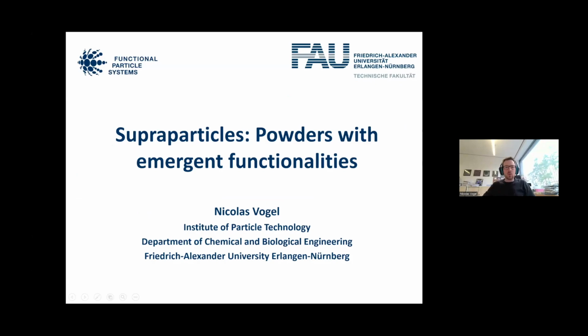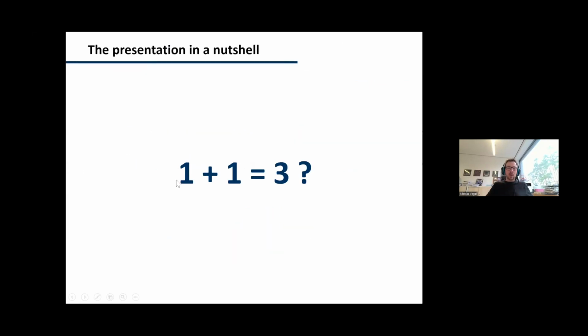What I want to talk to you about a little bit is supraparticles and what those are and why we think those are interesting. To a certain extent, this complements what Lutz has talked about quite nicely, because in our case, everything will be wet. We typically come from dispersions, so particles in aqueous solutions, and not from flames. But I still want to show you what we can do with such defined particles. In a nutshell, that is kind of what I want to convince you about. We take small particles and we make them into larger particles, and out comes something that is more than just the sum of its parts.